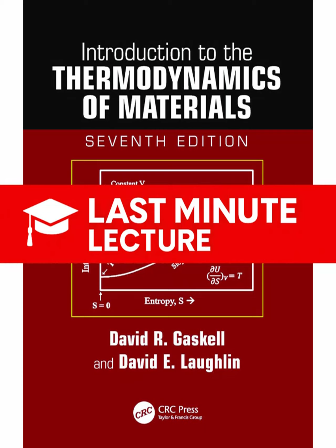Which brings us to the function that really rules the world of material science, the Gibbs Free Energy, G. The gold standard. Defined as G equals H minus TS. And it's so important because virtually all material synthesis, processing, and testing happens at constant temperature and constant pressure. And that combination, constant T and constant P, is what gives G its incredible power. Its change, delta G, dictates the maximum non-PV work you can get out of a process. So things like electrical work from a battery. Exactly. So if a phase change can happen or a reaction can occur, it absolutely must drive G down.